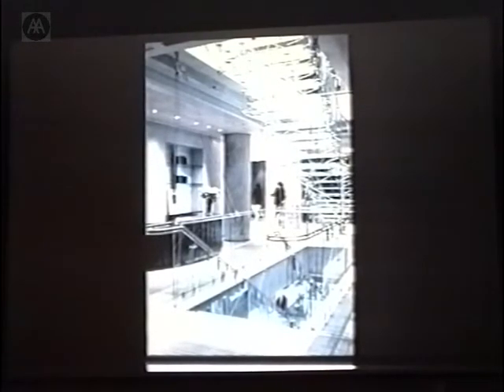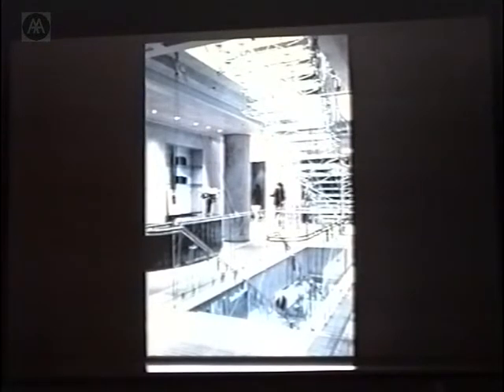So she finally thought, well, why have the aluminium tray? Why don't we just use the acrylic? And in fact, it's quite a subtle result, because you couldn't use the acrylic on its own because it scratches very badly, and it's terribly flexible, so it would become very, very thick as a material. And the glass is ordinary annealed glass, so it's not toughened or laminated, it's just a sheet of ordinary annealed glass. And the whole way this works is that if the glass cracks, then the acrylic tread, which is underneath it, quite simply holds the glass till you come along and replace it.